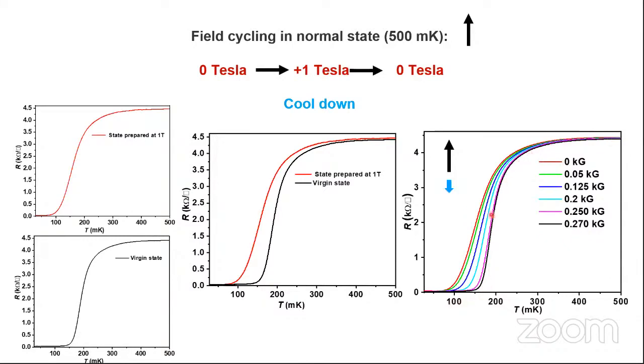So from this, we speculate that there is a remanence directed in the opposite direction with respect to the applied magnetic field, which is there at the interface, and which is a consequence of the field cycling in the normal state. So that means the interface retained the memory of the field cycling in the form of a negative remanence. When I apply a magnetic field upward while the remanence is downward, because this is negative, field cycling was done in the upward direction, the applied magnetic field for measurement first compensates for the negative remanent field that is already present. And we estimate that to be 0.27 kilogauss.